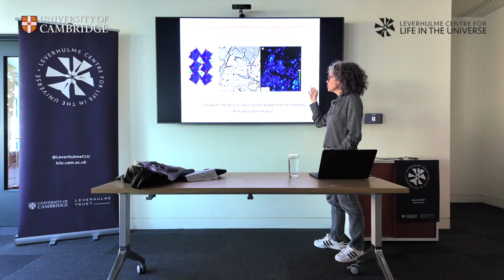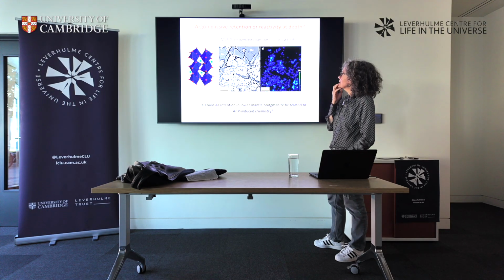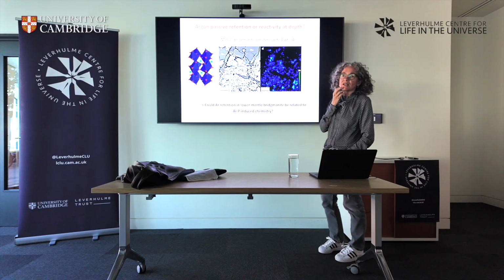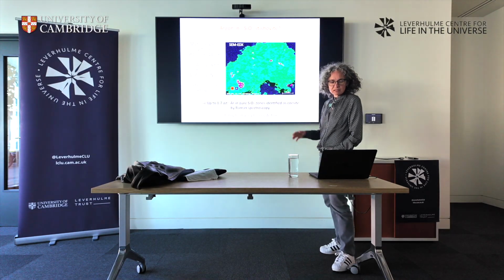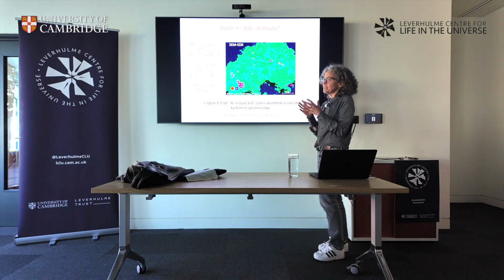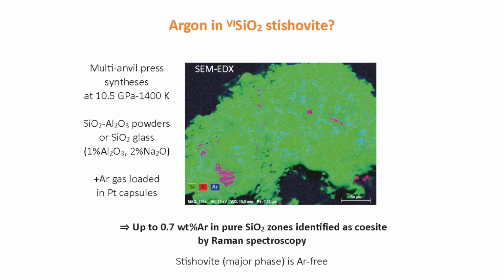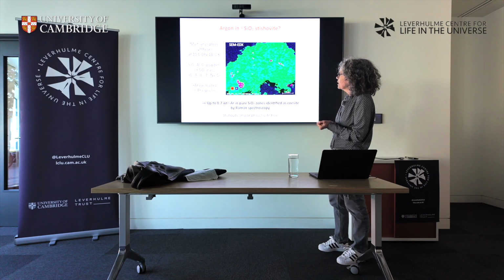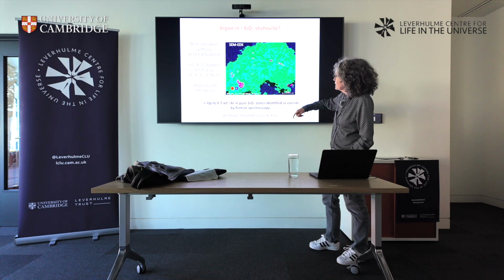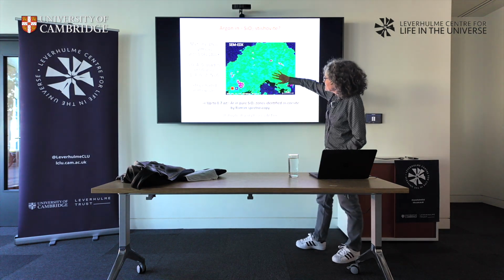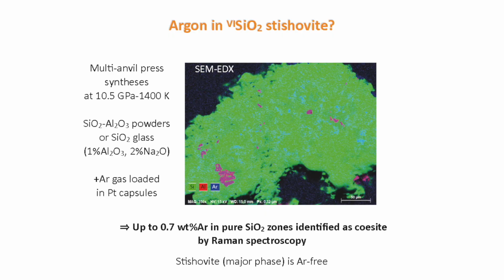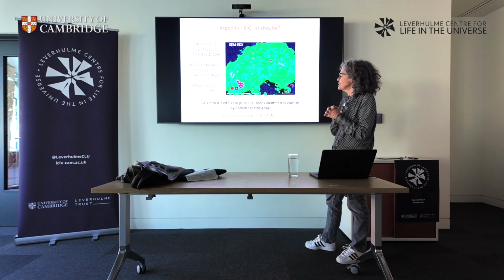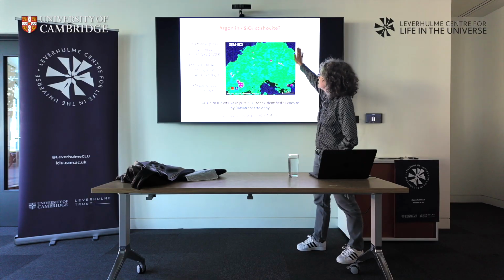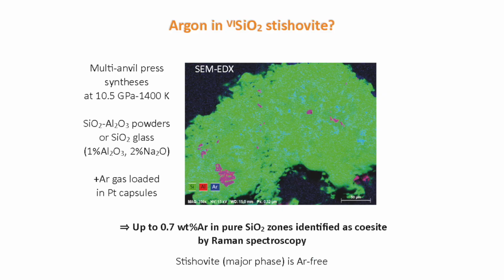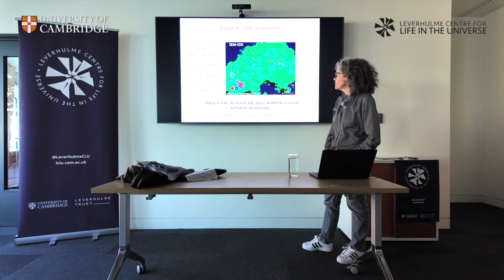So before going straight to bridgmanite, we decided to go slowly, as we did for xenon, and start with SiO2. Let's see what happens when we squeeze argon with SiO2. The SiO2 phase which has silicon in octahedral sites is stishovite. On multi-anvil presses, we ran experiments and recovered the sample, and in a few cases we did observe argon. That's an SEM image, where it's blue, it's argon. In some cases we also added aluminum, thinking that maybe that would help with charge balance. Most of the sample has no argon at all, but there are some locations, and those are not bubbles, where you do have quite a lot of argon.